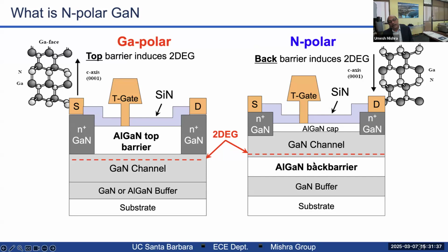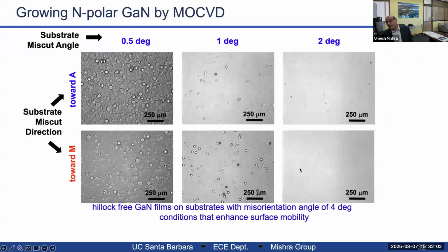So then the nitrogen polar device has the following. It has AlGaN at the back, GaN on the top. And then you have these ohmic contacts, N plus GaN ohmics, and they basically connect to this 2-dimensional electron gas. Okay, so this is very nice because you're making a contact to a low band gap material, easy to make contacts, and you have a back barrier as well. And I'll come to the advantages in a minute, but let me tell you what the problem was.